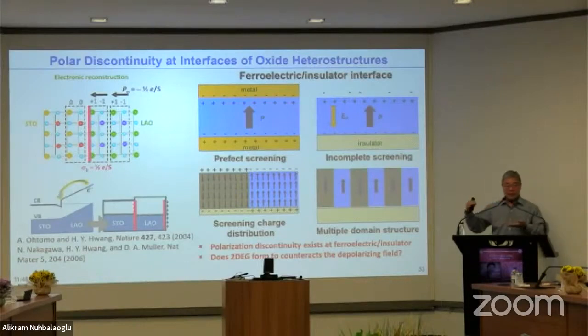With the system having some free carriers, the free carriers with the opposite sign of charge will be trapped at the interface. The trapped charge cannot leave the interface, but can move around the interface. This will form a two-dimensional carrier gas. If electrons are trapped to compensate the positive bond charge, you have a 2D electron gas. If holes are trapped to compensate the negative bond charge, you have a hole gas.